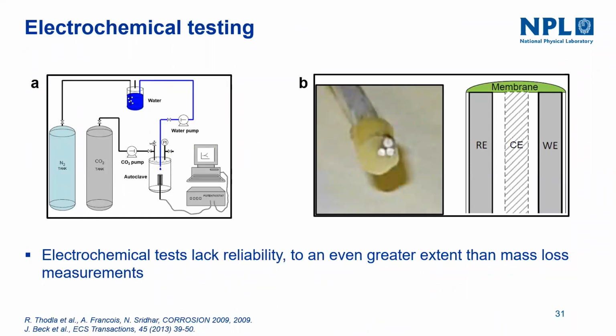Now we discuss the electrochemical measurements. Electrochemical measurements normally can give an understanding of the corrosion mechanisms and also determine instantaneous corrosion rates. But they also have reliability issues, to a greater extent than the mass loss. The issue is that the condensed phase is very low in volume, so it can't normally wet conventional size electrodes. So people have miniaturized these electrodes so that the condensation on them can provide electrochemical understanding. But still, we can't polarize the electrodes to very high potentials because of the low volume.